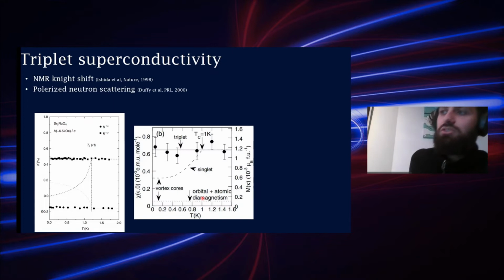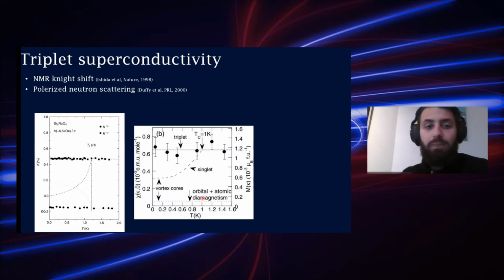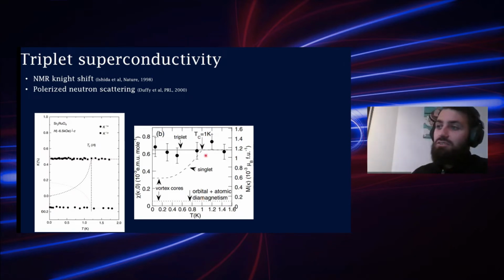Also, with polarized neutron scattering, similar effects were found, and so the spin susceptibility is not suppressed below TC.